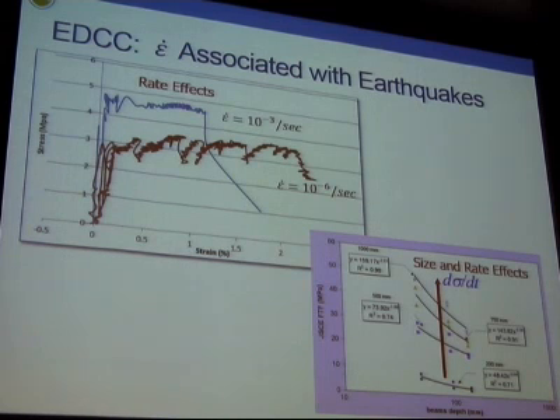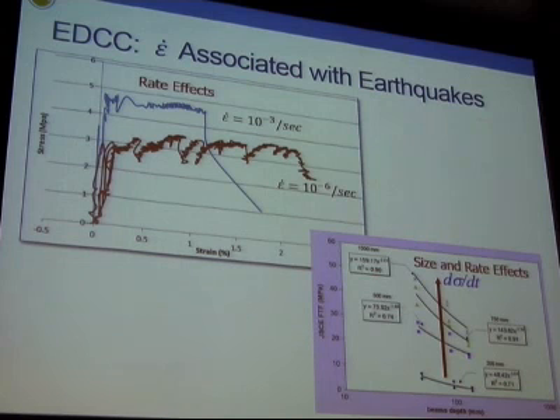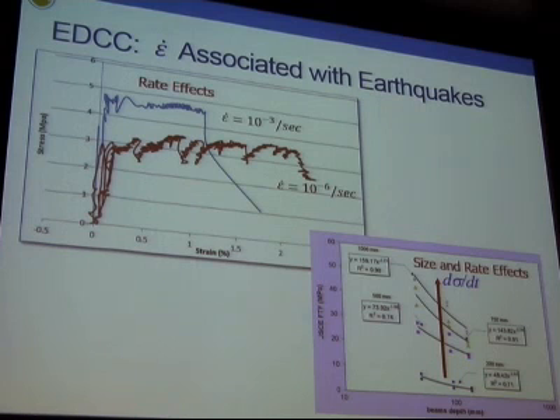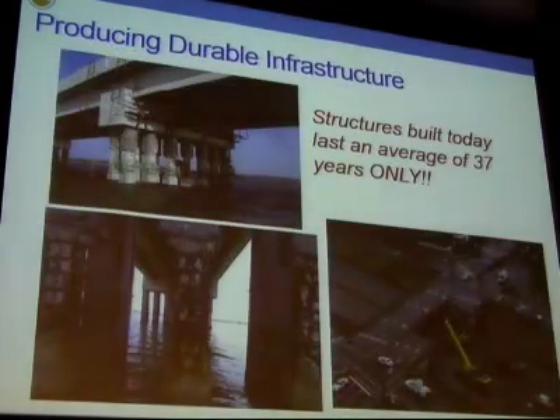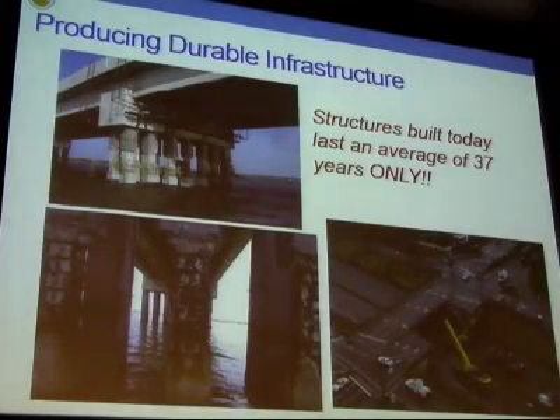There's also an influence of size. So if you prescribe to Bazant's size effect law, you'll notice that in fact the energy absorption capacity reduces as I'm increasing the size of the specimen. And you'll also notice that the curves become much steeper as I'm increasing the strain rate. What that means is size effect becomes even more important when you're having materials which are being strained at high rates of loading. This brings me to the last two topics that I want to briefly talk about.